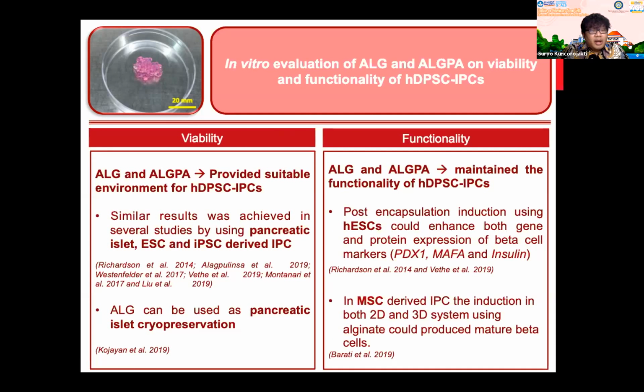Another study on pancreatic islet cryopreservation incorporated with alginate encapsulation reported that the alginate encapsulation could maintain both viability and functionality of pancreatic islets. And according to the functionality evaluation of the mesenchymal stem cell derived IPC that we produced here, in alginate and alginate pluronic acid, the result of this study showed that this encapsulation platform could maintain the expression of pancreatic endoderm and pancreatic beta cell gene markers for at least 40 days, the time that we used in this study.